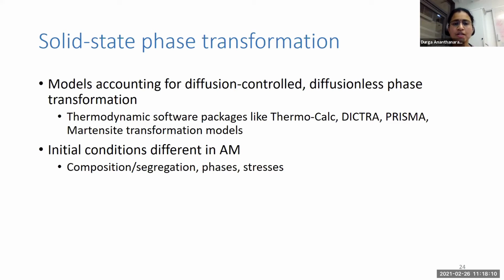Then solid state phase transformation. We already have a lot of models accounting for things like diffusion controlled phase transformation, diffusionless phase transformations. And there are several thermodynamic software packages like Thermo-Calc, DICTRA, PRISMA, and other models that predict, say, martensite transformation. All of them in principle can be used to predict AM structures as well from the point below solidification. But one thing to keep in mind would be that we have very different initial conditions that we have to input to these models, because we have a certain level of segregation due to the process, and the phases formed could also be very different because of this extra driving force that we have, plus the effect of stresses also. So when we capture all of these initial conditions, we can still use the models available for solid state phase transformation.